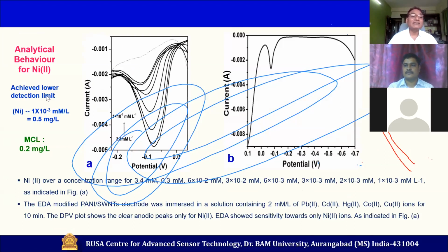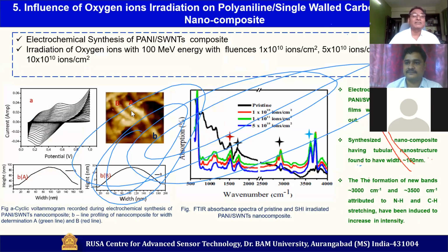And then we went ahead and tested it for detection of Ni, nickel, right? And here, to our surprise, the MCL level was 0.2; we could reach very close to that 0.5. Although still it was better than reported data, and therefore we could publish it in a good journal. And then we also explored the effect of SHI irradiation.